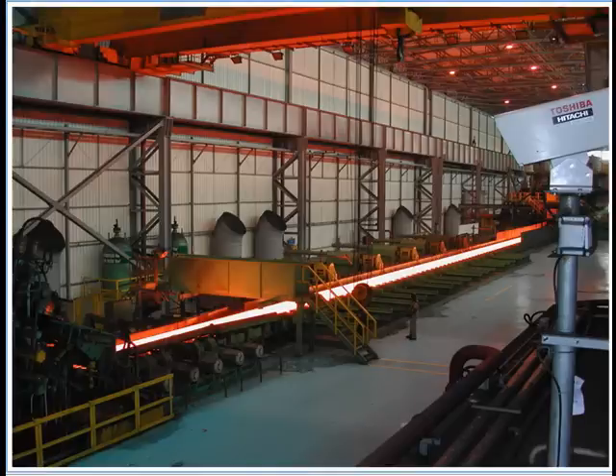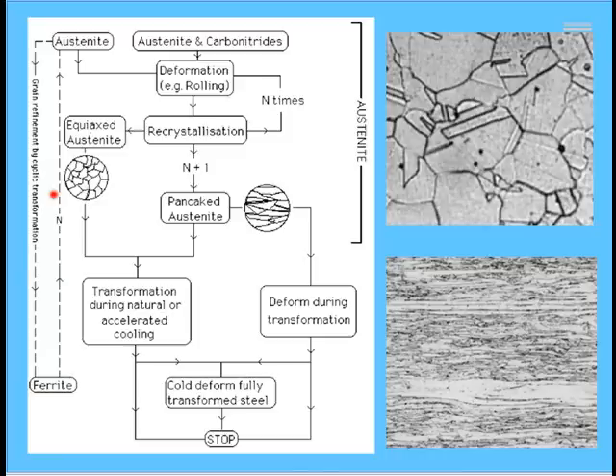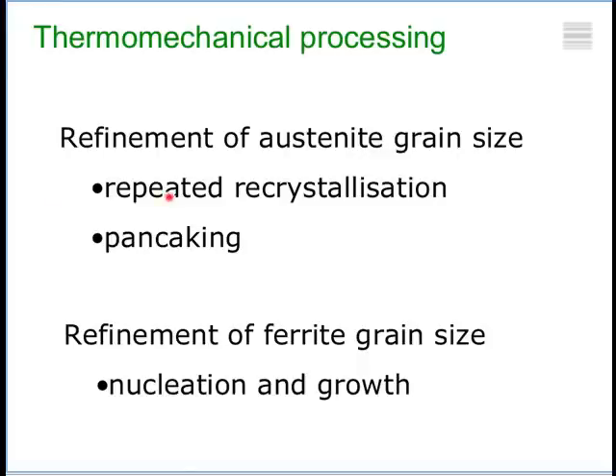So the question is, can we take this process further? The process works by severe deformation. So you start with grains like this, and the boundaries of these grains are pinned by fine niobium carbide. You deform it at a temperature of around 1200 degrees centigrade to get these pancake-shaped grains, and then you allow it to transform. And typically, grain sizes of 10 micrometers are nowadays routinely obtained. The process works, as I said, by refinement of the austenite grain size, which is recrystallized repeatedly, and grain growth is stopped because of these very fine particles of niobium carbon nitride. And if you have fine austenite grains, you will also get fine ferrite grains.